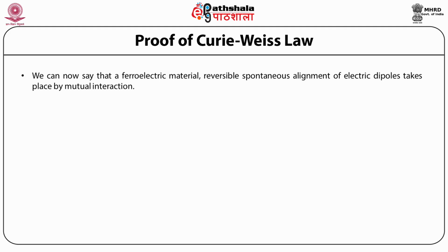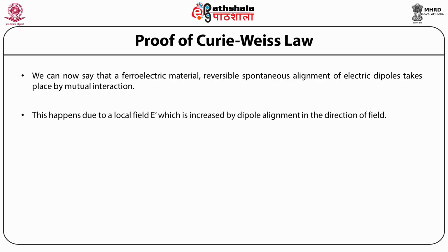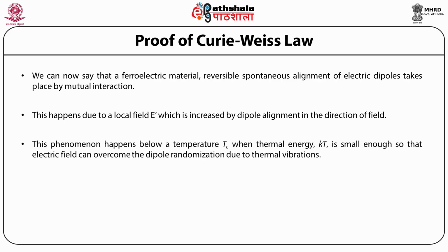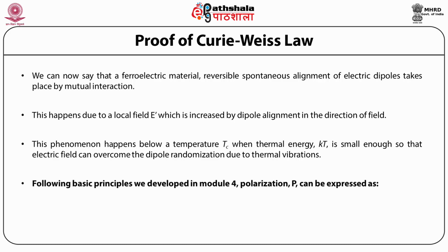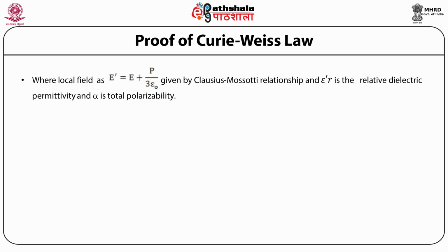Proof of Curie-Weiss law. We can now say that in a ferroelectric material, reversible spontaneous alignment of electric dipoles takes place by mutual interaction. This happens due to a local field E', which is increased by dipole alignment in the direction of the field. This phenomenon happens below a temperature Tc when the thermal energy, that is kT, is small enough so that the electric field can overcome the dipole randomization due to thermal vibrations. We know that the polarization can be expressed as P equals epsilon r prime minus 1 times epsilon naught E, which is equal to n alpha E', where E' is the local field, given as E plus P upon 3 epsilon naught, which is given by the Clausius-Mossotti relationship.